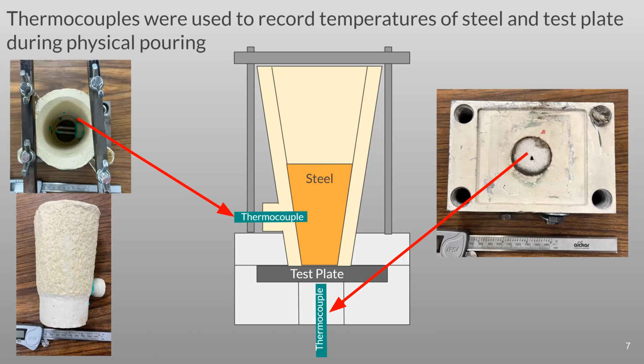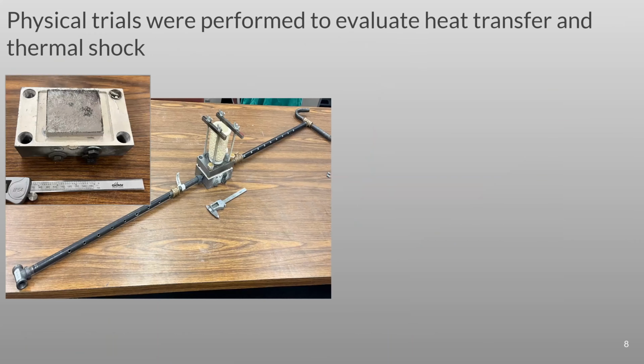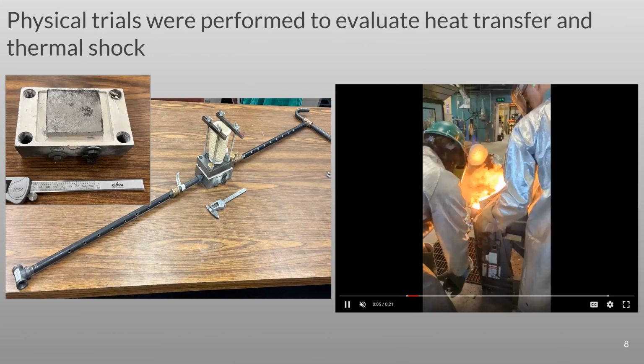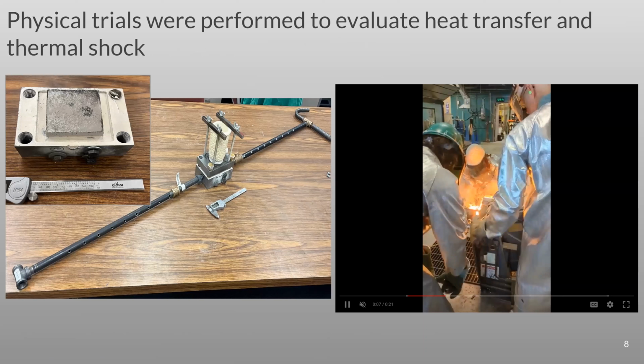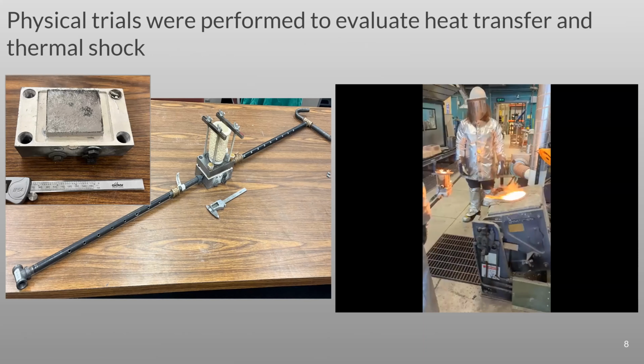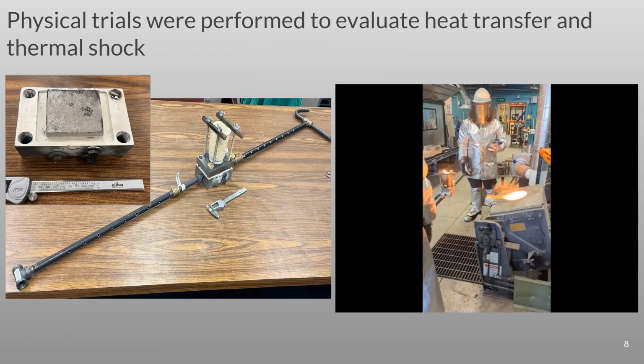A mold design was made to test the candidate material's response to the pour cycles with stainless steel. Thermocouples were used to measure the temperature of the candidate material and the molten steel being poured during each cycle. Physical trials were performed using the mold seen on the left. During each pour, molten steel was held in contact with the material for 6 seconds before being poured back out.